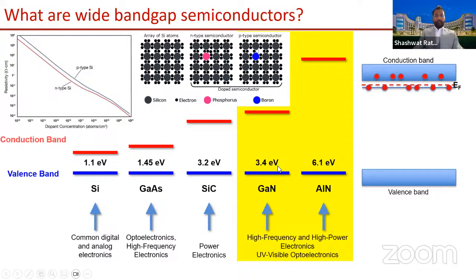Now, in wide bandgap materials, the material does not like to get doped at all. So what it will do as a response to doping is to incorporate some intrinsic defects, such as these, which now trap your electrons back and move the Fermi level back to where it started. So this is what makes doping in wide bandgap semiconductors a formidable challenge. And this is why it was so difficult to even dope these materials to modest levels.